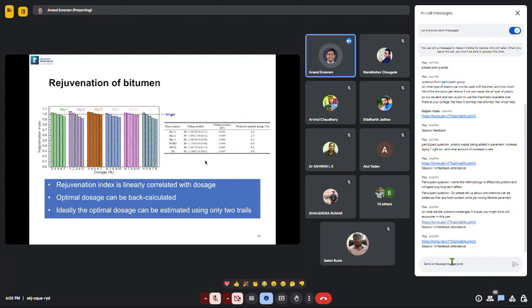Some of the main results that we saw is that by developing these rejuvenation-based indices, we can linearly correlate them with dosage. Then using that, we can back calculate to determine the optimal dosage, and we can determine it based on only 2 trials. Mixing a high percentage of modification and a low percentage of modification, and then using a fitting algorithm, we can find the optimum percentage that we need to modify our materials.